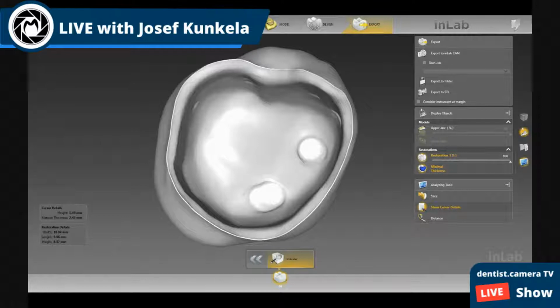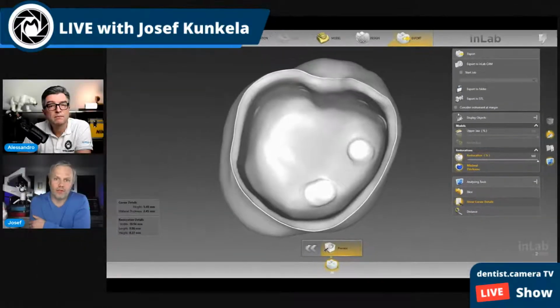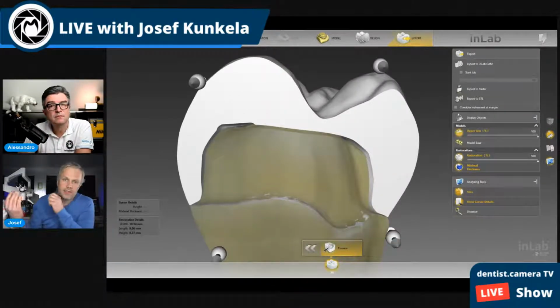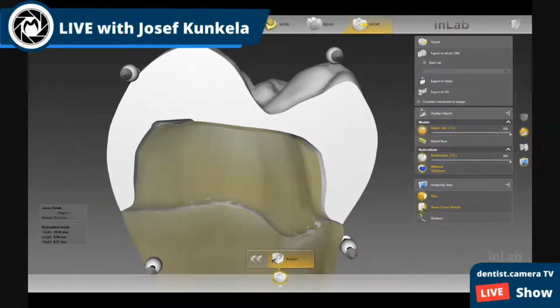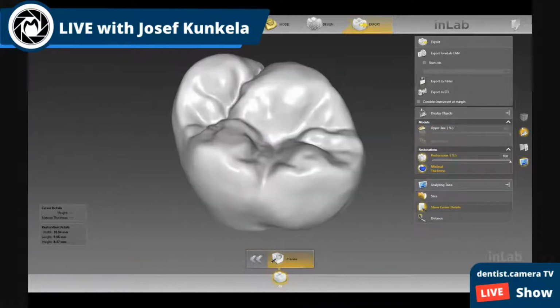Cracks can appear during function or during the dry try-in, because if you do not check your milling proposal again against your virtual model, you don't know how the software reduced the minimal thickness you preset before. This is what you can avoid with the printing process. Here is a section view. You can see the over-milled part, but the spacing for the printing was really rounded, and you can still see just a small over-milled surface.